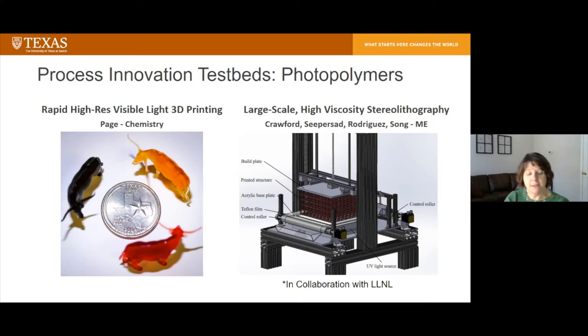And one of the really unique things about it is that with wavelength selective chemistry, this process enables graded parts. So you could have, for example, hard and soft joints. On the right, we have a large-scale, high-viscosity stereolithography machine. And this is something that I'm involved in, along with Dr. Rich Crawford and some of our graduate students in collaboration with Lawrence Livermore National Labs. This particular machine is aimed at printing very, very high viscosity resins in stereolithography, and then being able to do this over a very large scale without damaging the fine features of parts.